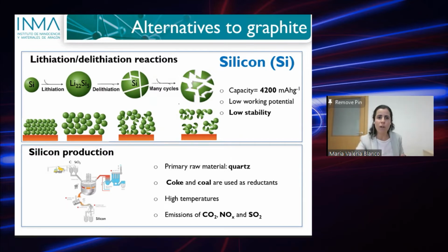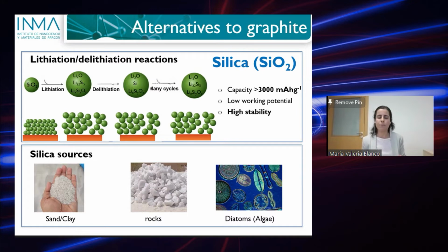Another alternative to graphite is silica. Silica has been proposed quite recently as an anode material because, as you might know, silica is an insulator, so normally it's not the first option when we think of using silica for a battery. But some studies have shown that silica works quite well. It has a theoretical capacity that is very close to that of silicon and still much, much higher than that of graphite, and it has much higher stability than silicon. This is really interesting, and that's why it's a nice option to explore as an anode candidate.